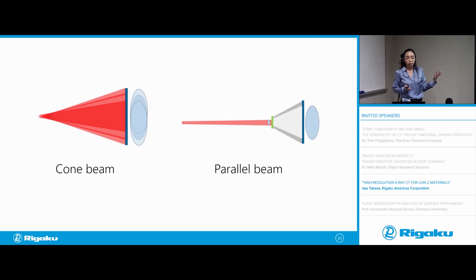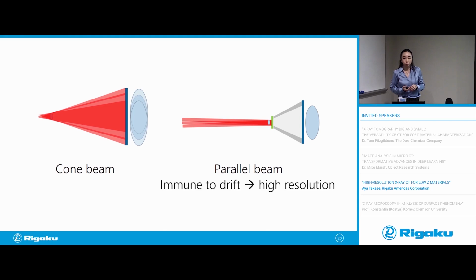And this is one of many reasons why the resolution you can achieve with the cone beam geometry is somewhat limited. But with the parallel beam geometry, because we're not using beam divergence, the source is going to drift anyway, but that drift is not magnified. And the sample is sitting pretty much right up against the detecting system, so you don't need to worry about imaging being blurred. This is why the parallel beam geometry is considered to be more or less immune to the source drift and the source size limitation too. And it is a really good geometry to use for high resolution measurement.